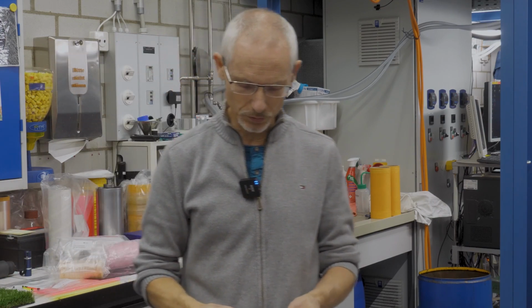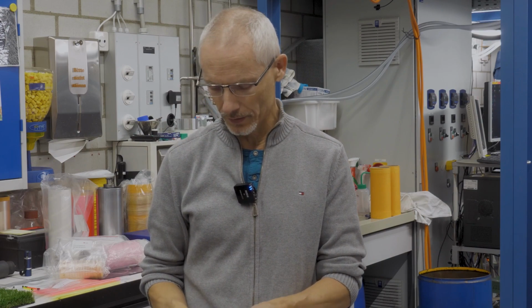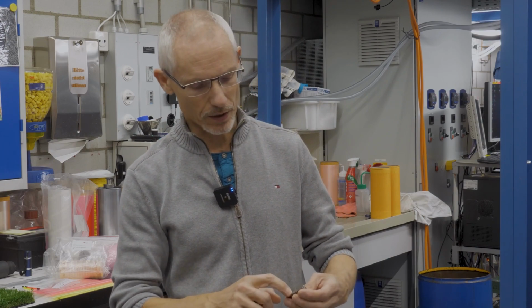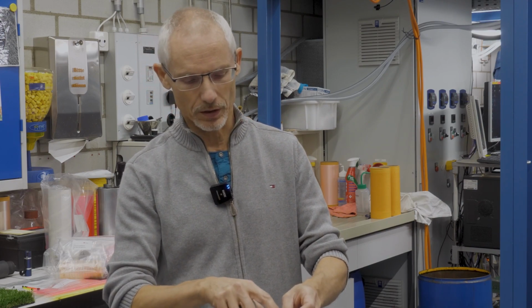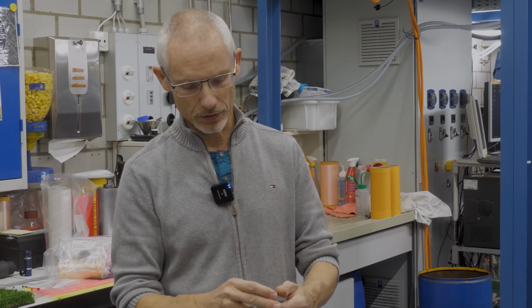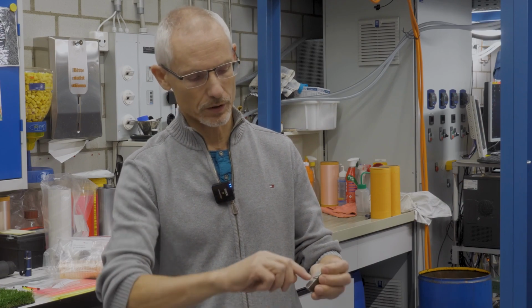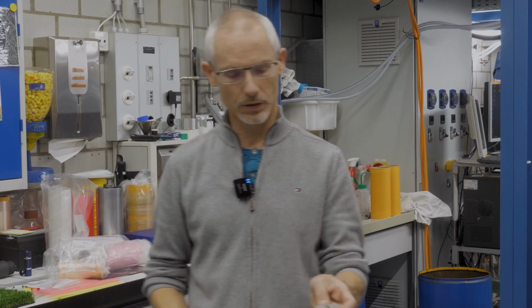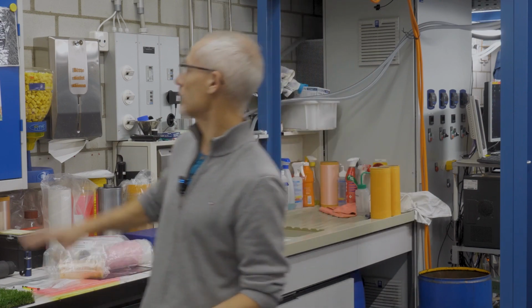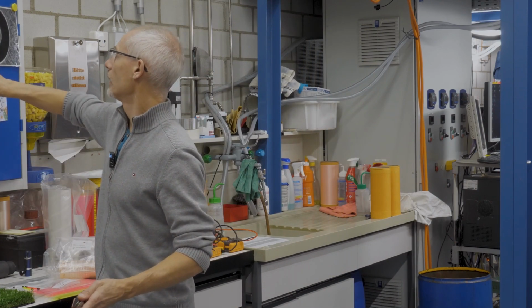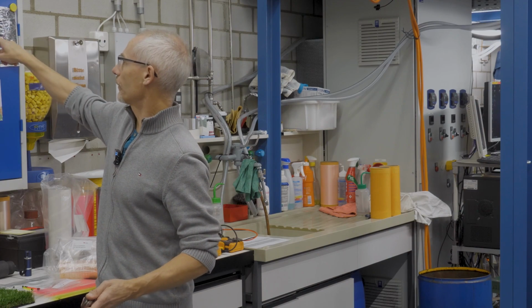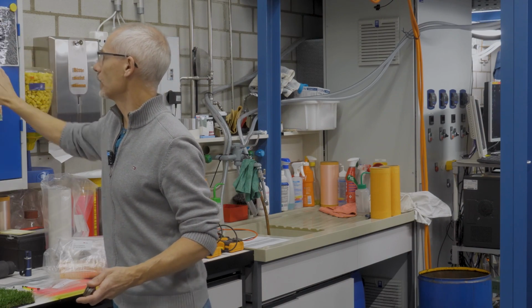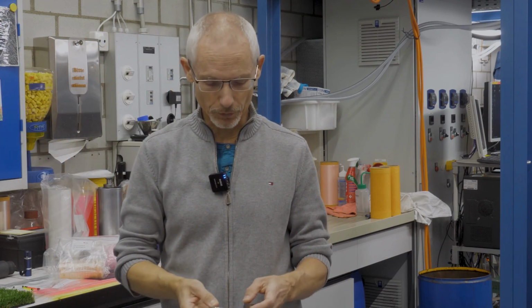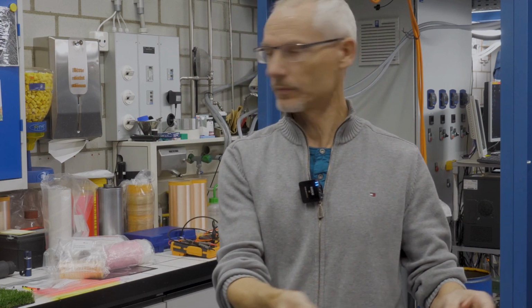So this is two times the same spinneret, here just cut in half, and we can see we have one material coming from the side, which then fills the annulus, and then we have another material which goes into the center, into the core. And in the end, this is a blow-up of the spinneret, where we have the core material and the sheath material processed together to form a filament.